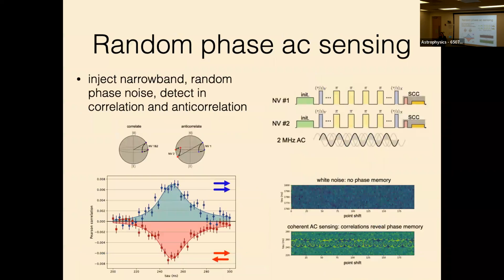Okay. And then finally, we can also just inject sort of a narrowband tone at 2 megahertz, and then intentionally randomize the phase, and then see whether or not we can see that in correlation for both NV centers. And we indeed see this very beautiful correlation around where we expect to see a 2 megahertz signal.